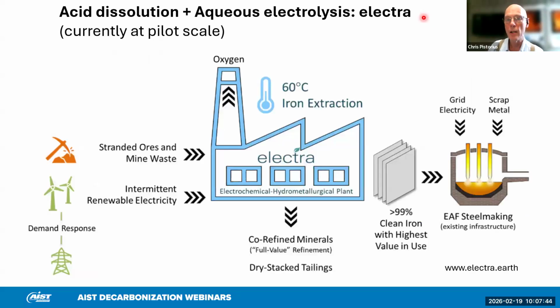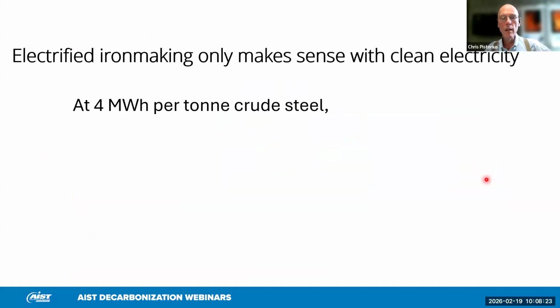The alternative process developed here in the US is the one of Electra, which dissolves the feed material in acid, so somewhat classic hydrometallurgy, and then uses large-scale electrolysis to produce cathodic iron, which then is a very clean feed material that can be used in normal electric furnace steelmaking. In fact, it's a good material for specialty steels as well. Again, it's being run at large pilot scale and being scaled up soon. So all of these, the numbers add up to around 4 megawatt hours per ton.